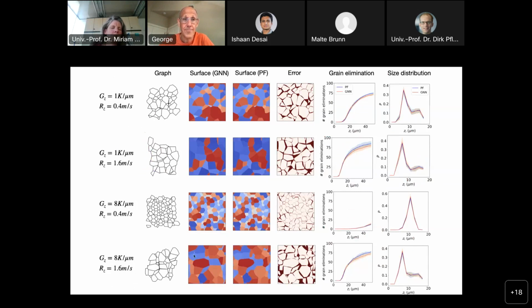And this is the reduced order model, and this is the phase field calculation. You can see the errors again can be quite significant. There is curvature here, which is not captured at all in our case. The grains have different shape. So the point-wise errors can be up to 20%. However, as we go up in height as the process continues, the percentage of grain elimination events is very similar between the two simulations. The red curve is the reduced order model, the blue curve is the phase field, and the shaded areas are the variation across different runs. And you can see we can capture the elimination events quite accurately in the different regimes, and also the size distribution, this quantity of interest, between the two.